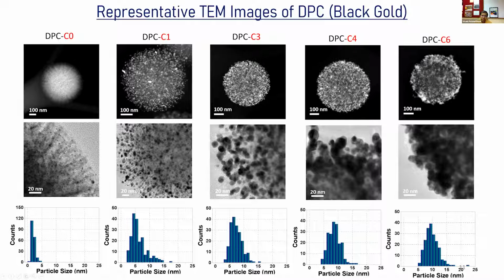I'm just showing some representative ones. And you see when you go from C0 to C1 to C3, C4 to C6, the particles are coming closer, they are getting crowded, and at C6, in fact, they started connecting. Even at C4, some of them are connected. So at C4 they are very close, whereas at C6, they are connected. So now we wanted to know which one is the best material, because we were not knowing what is the perfect, optimized gap between the particles that is needed for better light absorption and catalysis.